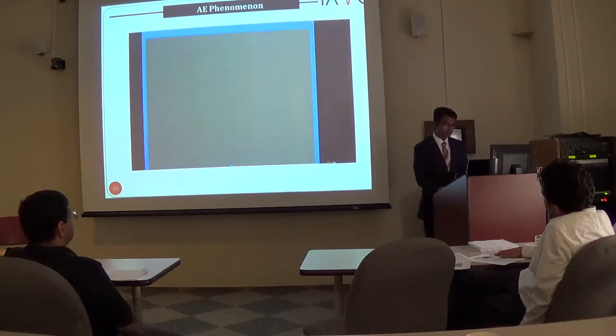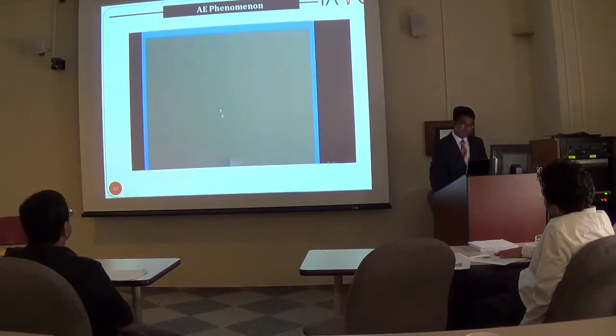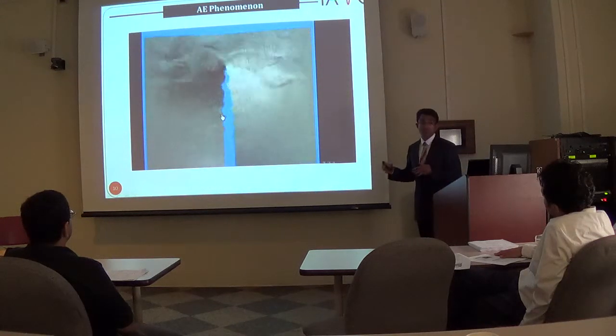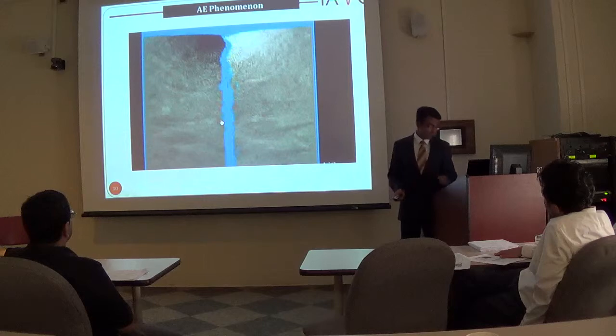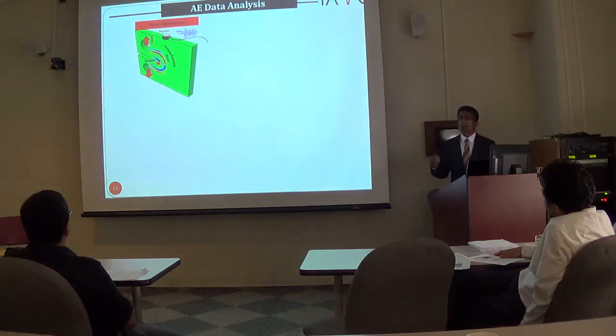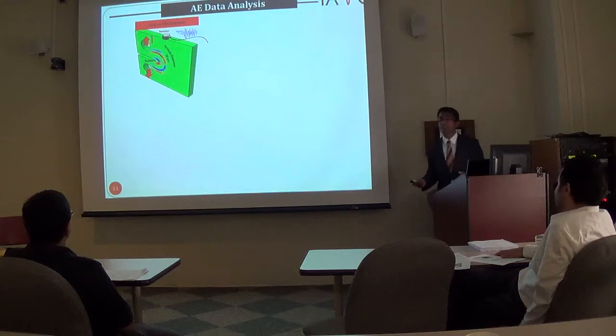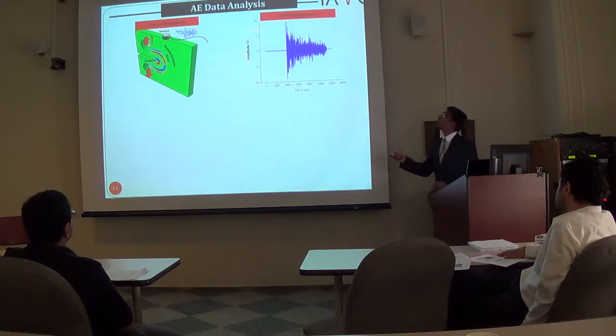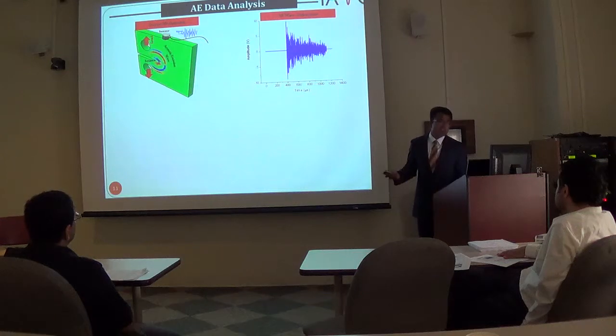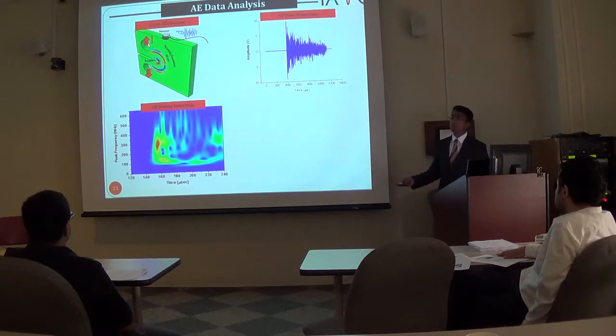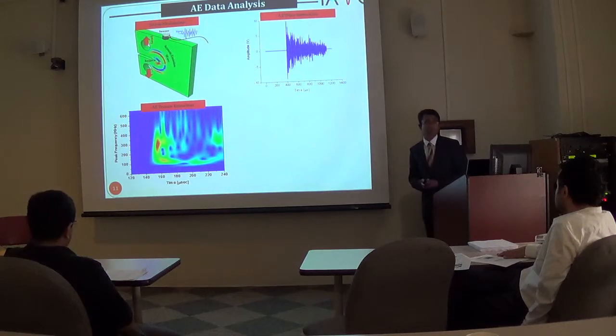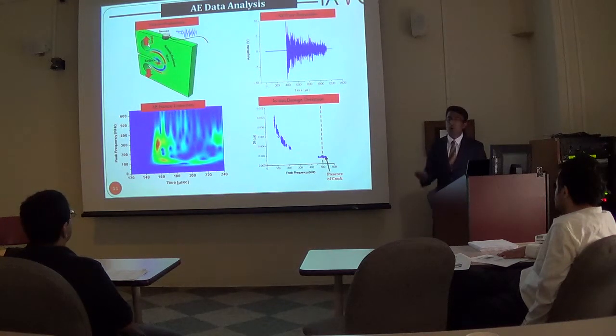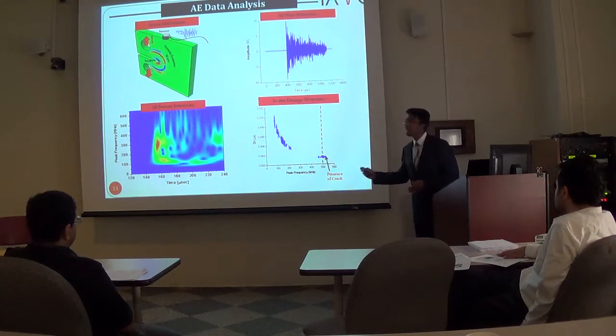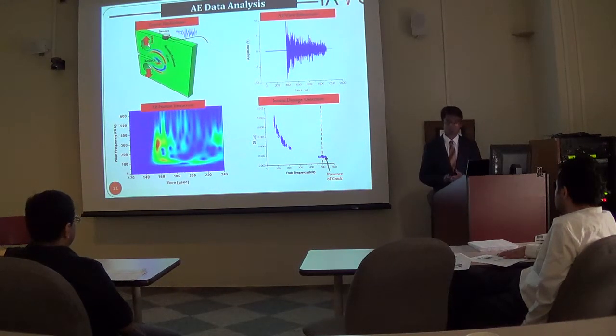Now, to further illustrate the concept of acoustic emission, I'm going to show you this video that shows how acoustic emissions are produced in the material and propagate due to a specific damage source, in this case, cracking in the plate. You can see as the crack grows in the plate, the release of stress waves, which is the acoustic emission that propagates in the medium and can then be picked up by sensors that are either strategically placed at certain locations or random locations. The waveforms that are detected are of similar characteristics as the one shown here. Advanced signal processing techniques are then applied to extract features such as frequency analysis and other sorts of analysis, and hopefully design novel AE damage detectors to reliably flag the presence of damage for real-time applications.